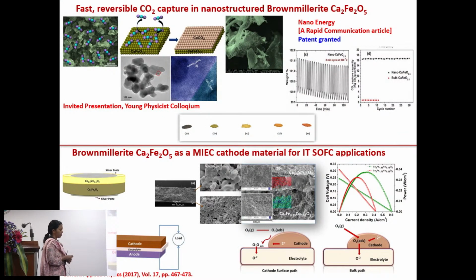What was interesting in this work was that a very fast reversible CO2 capture can be seen even at room temperature, and obviously the activity increases at the industrial flue temperature, which is 500 degrees Celsius. This was beautifully shown in the case of nano CFO, whereas in bulk CFO, or calcium ferrite, you do not see any such activity. If you are interested, you can refer to the paper.